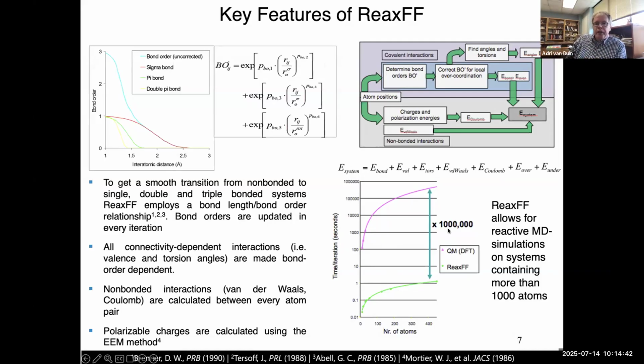So it's roughly about 1 million times faster than DFT, but the bigger the system gets, the better that comparison becomes, because ReaxFF scales roughly linearly with size, while DFT scales typically with N to the power 3. So if you double the amount of atoms, DFT becomes 8 times more expensive. ReaxFF just becomes about 2 times more expensive. ReaxFF is also fully parallelized, so there's a parallel version available within AMS and within LAMMPS. So you can run MD simulations on pretty large systems, easily 1,000 atoms and beyond.